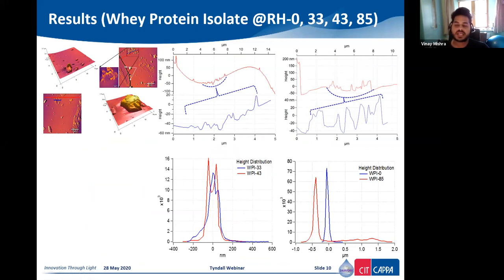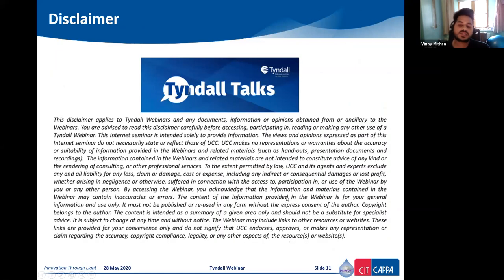Now, whey protein isolates again have almost negligible lactose content in them, and you can clearly see that the height distribution doesn't change much, either before or after the water required for lactose crystallization. There are no major height distribution changes, as there are no peaks of lactose. So this was the study which I did.